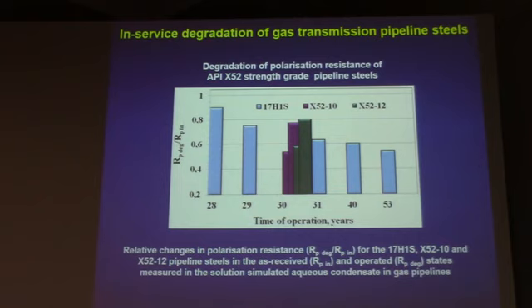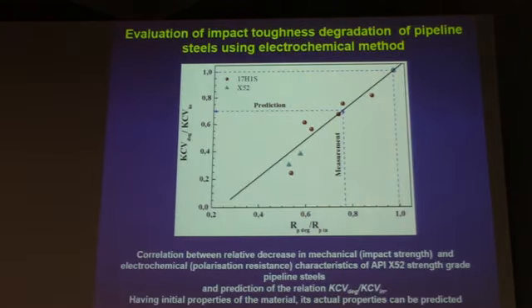This slide illustrates changes in polarization resistance for X52 strength grade pipeline steels after a different time of operation. And so the observed decrease in impact strength properties for these steels is accompanied by a decrease in polarization resistance. So not only corrosion degradation, but also degradation of bulk material properties can be estimated by changes in electrochemical properties for the material. And here presented an acceptable correlation observed between relative changes in impact strength and polarization resistance for pipeline steels